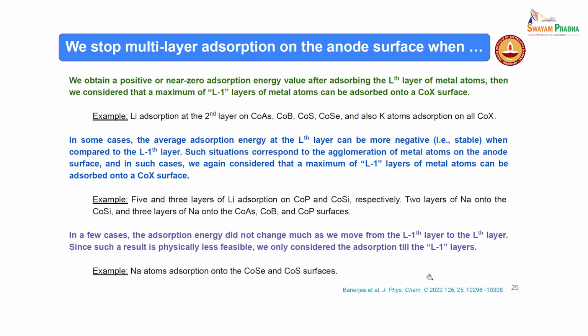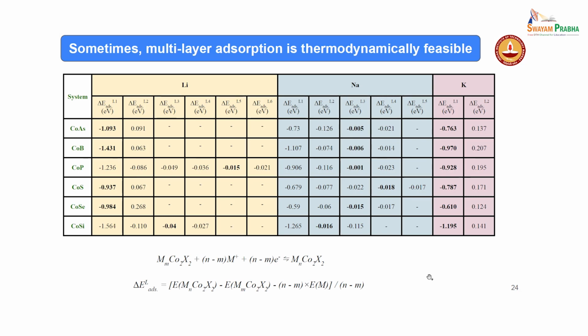For the earlier case, 5 and 3 layers of lithium adsorption on cobalt phosphide, if you see, here it was 0.015, but it started to increase once you go from 5 layers to 6 layers. That's why we stopped at the 5th layer itself. Similarly, for other cases also, here you see 0.04 to 0.027. Oh no, sorry, not this one. This is correct only. Where is the other one? So here if you see, the sodium case, 0.016 and 0.115. Suddenly it is increasing, 0.016 versus 0.115. That is very high. That automatically suggests that there is some agglomeration happening. That's why we don't want to consider that.